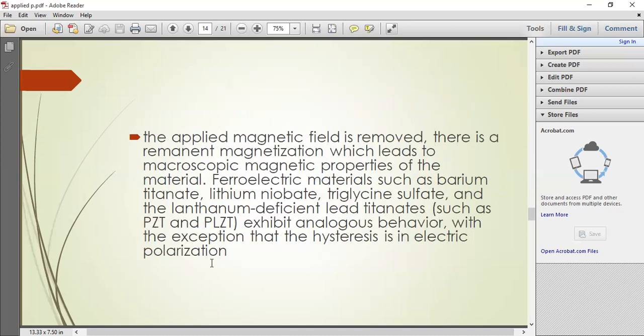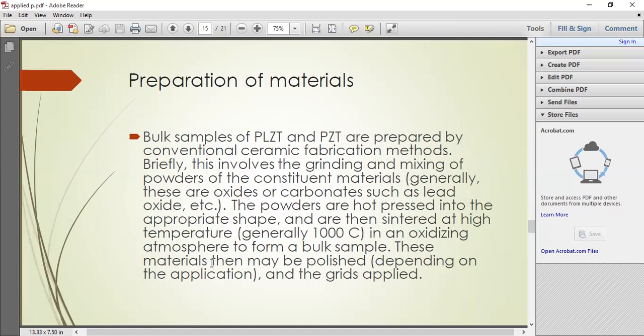When the applied field is removed, there is a remaining polarization which leads to macroscopic properties of the materials. Ferroelectric materials such as barium titanate, lithium niobate, triglycine sulfate, and lanthanum doped lead zirconate titanate exhibit hysteresis behavior. Bulk samples of PLZT are prepared by conventional ceramic fabrication methods.